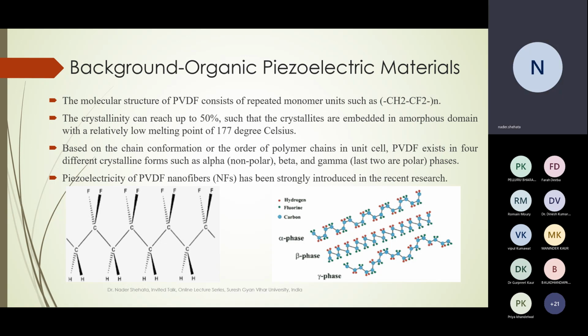Here we have to mention from the beginning that the main phase that we need for energy harvesting applications will be the beta phase, the middle one, because this beta phase is the best from the perspective of piezoelectricity, because this phase has a majority of oriented dipoles. So the upper side, for example, could have a majority of positive. The downside could have the majority of negative, or vice versa, depending on where the fluorine is and where the hydrogen is. But in this case, it's more dipole oriented compared to other phases, such as alpha phase and gamma phase.